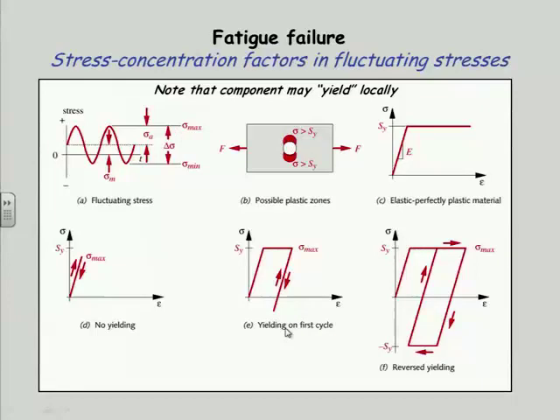But it yielded. If I had very large negative stresses as well, in other words, if my compressive component here went beyond the compressive yield strength, I could yield on both sides, and then I'd have a band like this, and I'd go around this all day long. If my maximum stress is not sufficient to pass the yield point, then I just run up and down on the elastic piece all day long. Right? So no yielding occurs. Well, if no yielding occurs, then there's no self-healing, no relief, and the crack can continue to grow. So that's the most dangerous case.